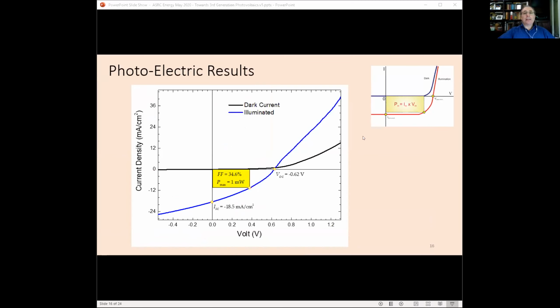So here's a result of our device and measurements. And I show this against the cartoon previously shown. We actually managed to get an open circuit voltage close to 0.6 volts, which is very decent compared to 1 electron volt theoretically. We get decent short circuit current. Our fill factor is low. It's about 35%. The best silicon solar cells show about 80%. But considering that that's the first device, I think we're doing pretty well.